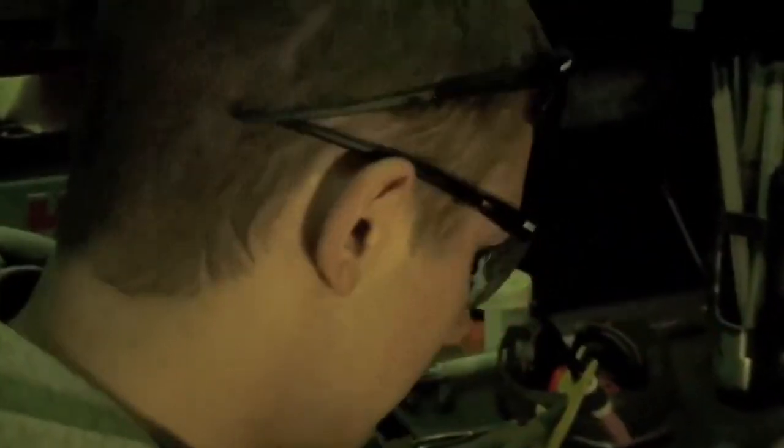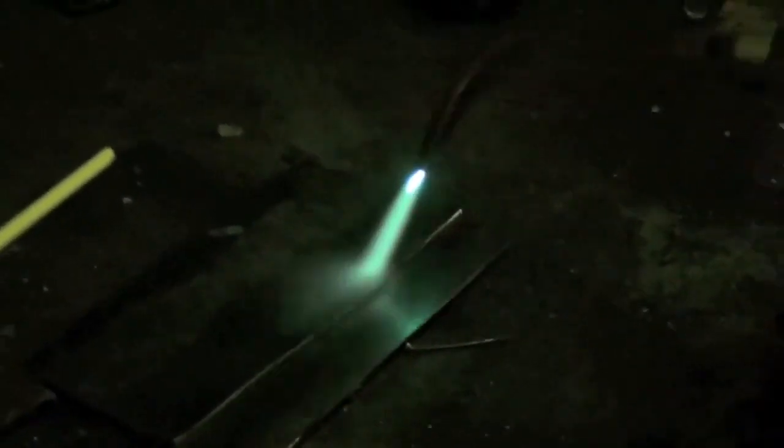We're going to come down here to our metal, put on our shade fives. These are just 14 gauge coupons, by the way. I'm just going to kind of heat this up to get all the moisture out. You can see it drawn out of the plate. Now we're going to get this almost a cherry red before we start to add the bronze. You have to be careful when you start adding the bronze. It'll run all over if your plate gets too hot, so you want to try and keep the heat pretty pinpointed to where you want the filler to stay. Opposed to running hot and fast, you want to do this cold and slow. I'm kind of dancing between these two plates to get them both evenly heated. We've got that color going on, so we're going to go ahead and introduce a little.